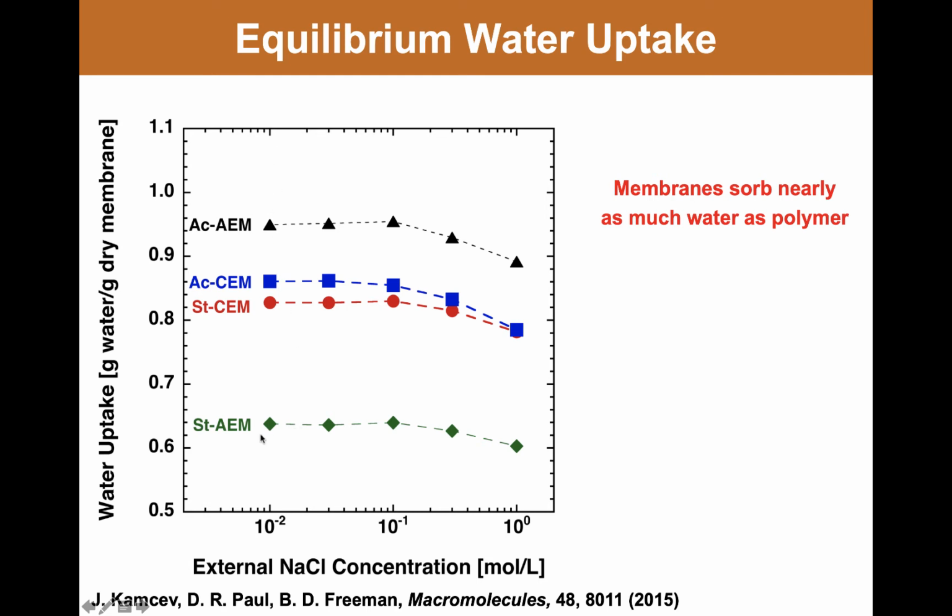The second thing to note about this is that the water uptake in these membranes depends on the concentration of salt in the solution in which the membranes are soaking. And as the concentration of salt that the membranes are soaking in goes up, the water concentration gradually goes down. And this is the phenomenon of osmotic deswelling.